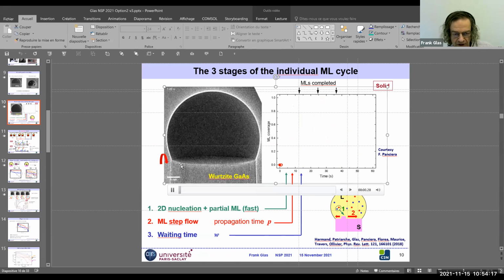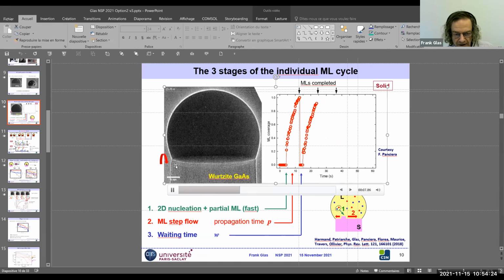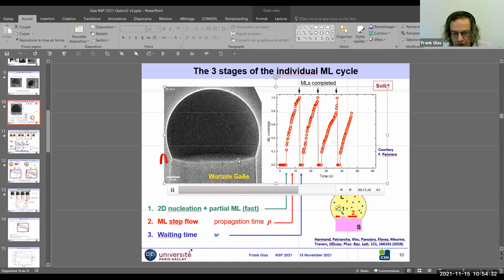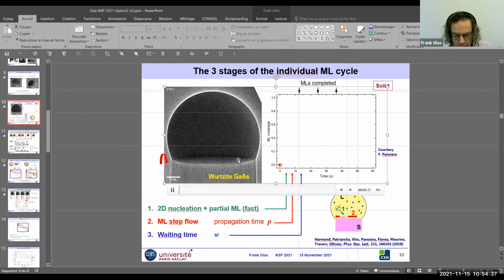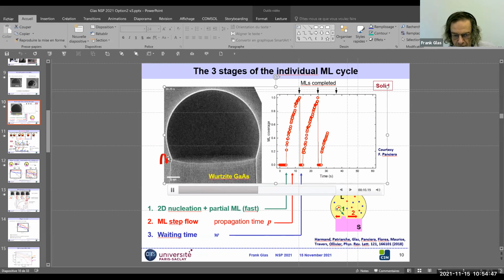So it's very different, because if this process is possible, you don't really need to wait for the refill by the external vapor phase. The system can use atoms which are already in the solid, it just prefers to transfer them from the already grown solid to the monolayer. And these atoms are available, they're there. And in fact, at the moment, even with quite a high resolution in our microscope, we could not observe the propagation of the monolayer, the cubic monolayer, across the interface. It's extremely fast. And we grow them in the same conditions.